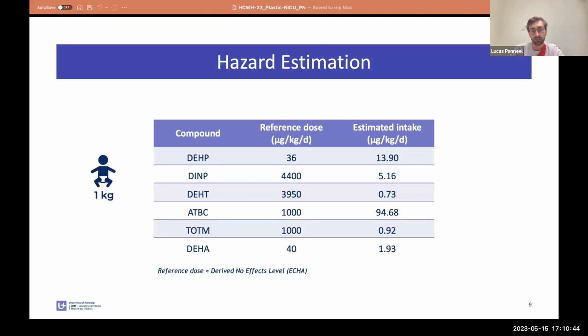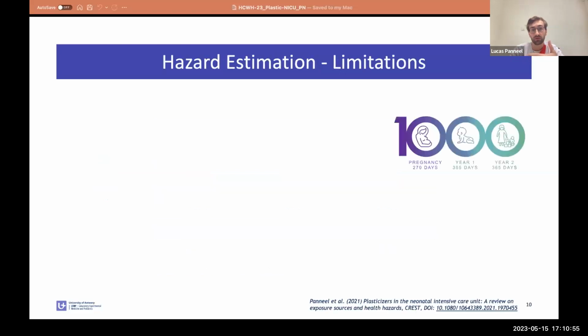So if you see this slide and compare to previous studies showing estimated daily intakes of up to 1,000 or 10,000 microgram per kilogram per day for DEHP, we can see a favorable evolution. Nevertheless, even though single compound estimated daily intakes are below the reference doses, there are some remarks to take into account before making full conclusions on safety of neonatal exposure. And first of all, as shown in our study, results show simultaneous exposure to different hazardous compounds at the same time, potentially causing an additive effect as suggested for different phthalates.